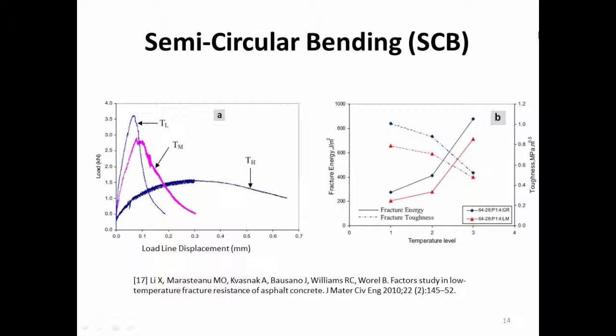We all know that when we put the asphalt binder into the mixture, it's a viscoelastic material, right? So when the temperature decreases, especially from -30 to 40 degrees, the viscoelastic properties of the material shrink. So the composite behaves more like a solid instead of a soft one, right? As you increase the temperature, the elastic property of the material is more and more dominant. The peak load decreases, but you get a much more relaxed curve.